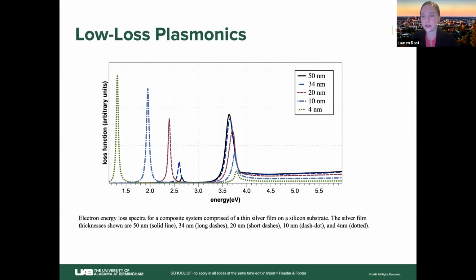So this figure shows this effect. What we have here in the figure, if you look at this, starting off at 50 nanometer thickness for a thin silver film on a silicon substrate. And these are calculated values. I'll talk more about how these calculations were done in just a moment. But the thicknesses go from 50 nanometers with the solid black line all the way down to 4 nanometers with the dotted green line. And you'll notice that for all of these, there are two peaks.